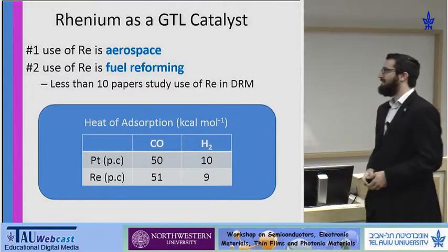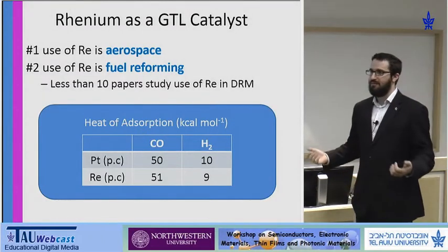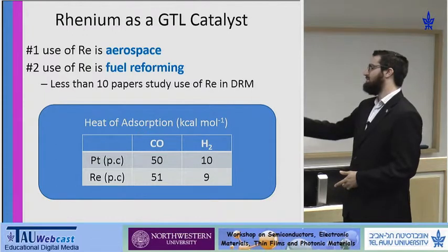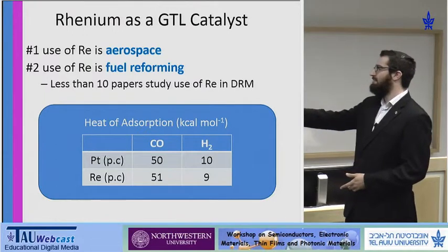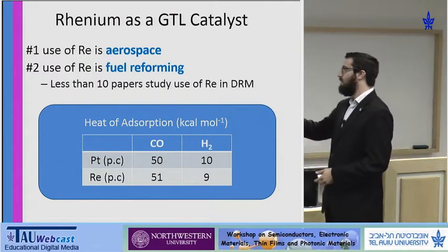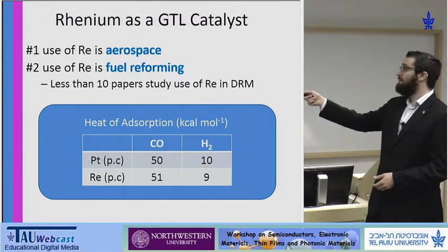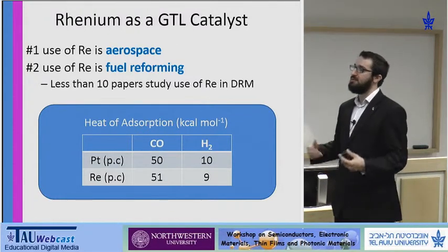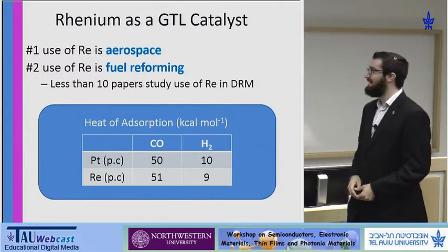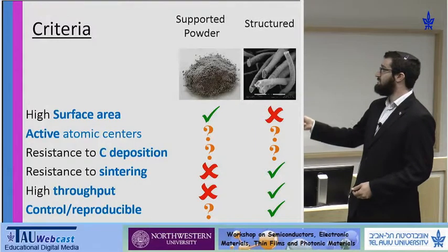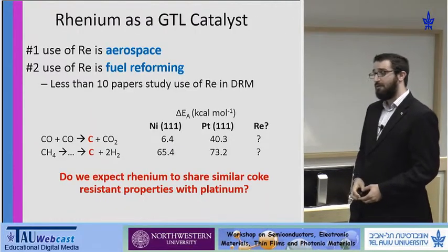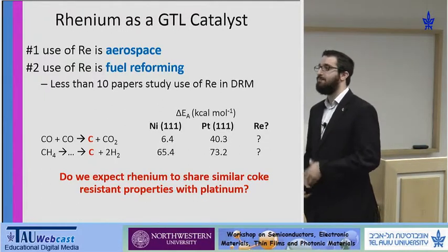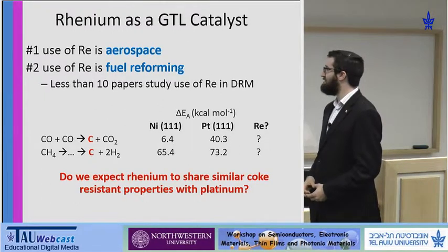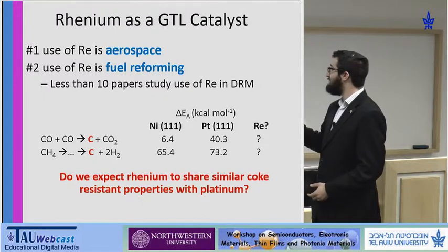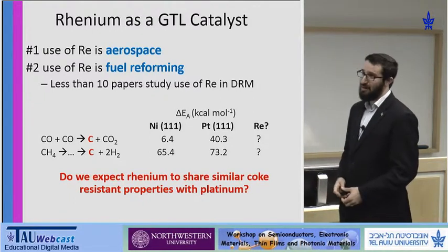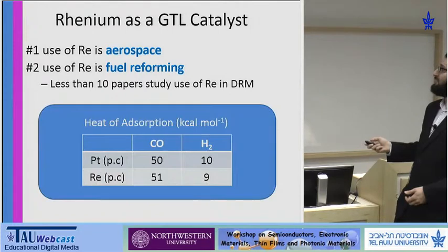And one thing that we can look at is the heat of adsorption of the relevant species involved in the reaction. So for instance, polycrystalline platinum and polycrystalline rhenium show almost the same heat of adsorption for carbon monoxide and hydrogen, which is an indication that rhenium would perform similar to platinum, which could perform as a coke-resistant catalyst. But we obviously want to minimize our use of platinum. And despite rhenium still being a rare metal, its price is about a third of platinum currently on the market.